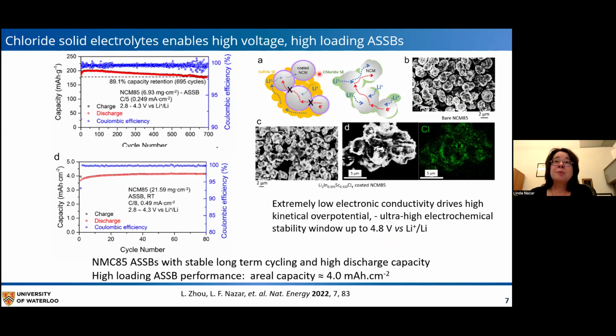So this works because if you compare this with an argyrodite type cell, where you have the cathodes coated, as I said, to protect them from oxidation, in this case, the electronic transport through the cathode composite is somewhat limited by these coatings. Whereas in the case of the chloride electrolytes, where you really have a patchy sort of coating, which can be seen here in these elemental maps, you have a patchy coating, and the cathode materials are simply compressed together, thus forming a continuous electronic pathway.